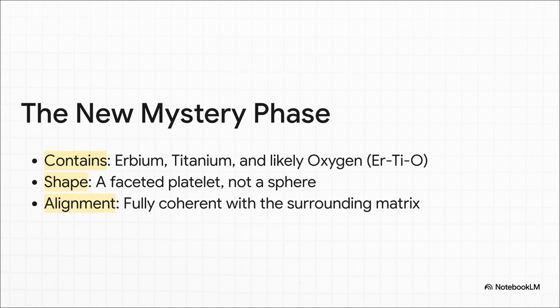This thing was a total curveball. Instead of just erbium and oxygen, this new particle also had titanium in it. And instead of a sphere, it was a flat, faceted platelet. But most importantly, it was fully coherent. It lined up perfectly with everything around it. This was a completely different behavior that only showed up under extreme heat.